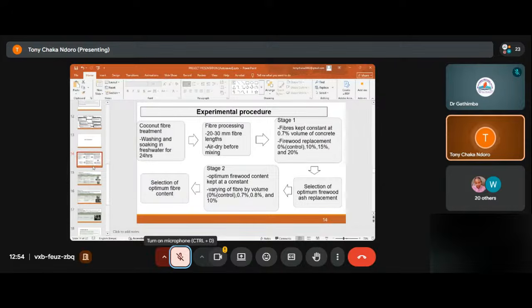The experimental procedure: coconut fibers will be treated by washing and soaking in fresh water for 24 hours at 20 to 30 millimeters fiber length and air drying before mixing. Stage 1 is here we'll keep from the literature review. We've settled on 0.7% volume of concrete to be kept as the content of the fibers. Firewood ash replacement will be 0% control, 10%, 15 and 20% for them in the cubes and the cylinders. Then we'll select the optimum